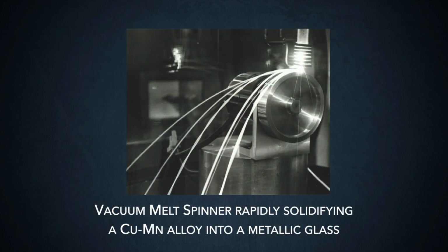And Danny, being a wonderful electron microscopist, took some of these flakes, which came out as flakes rather than ribbons, and looked at them under the electron microscope and found this unusual five-fold symmetry to it. And of course, that took on a whole life of its own, these so-called quasi-crystals that were formed in this material. To show how smart I was, I decided this was not something I wanted to get involved in, even though I could see how exciting this was, since it went completely against all my training at MIT on what sorts of symmetries are possible in crystals. They had to fill space, and therefore five-fold symmetry is completely forbidden.